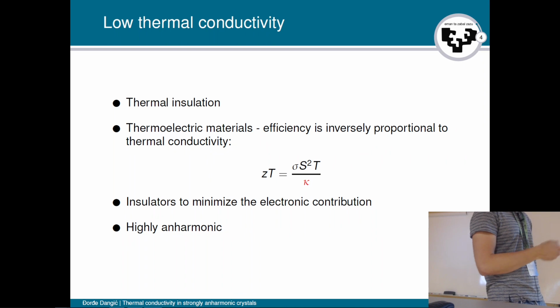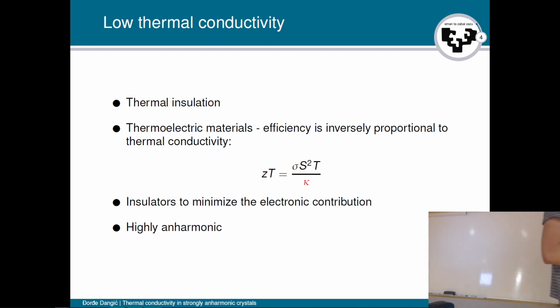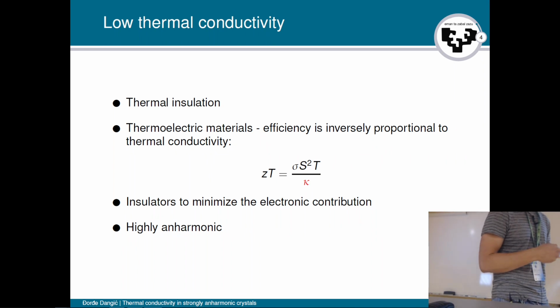Also, another way of reducing the lattice thermal conductivity is to make a material amorphous, so to break translational symmetry, and that leads to the scattering of the vibrations, and then leads to low lattice thermal conductivity.